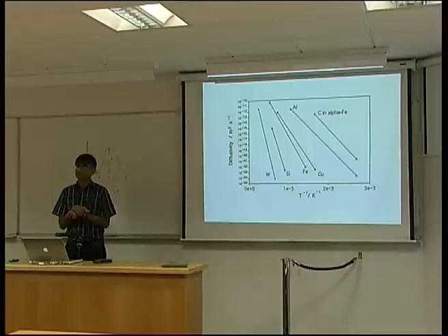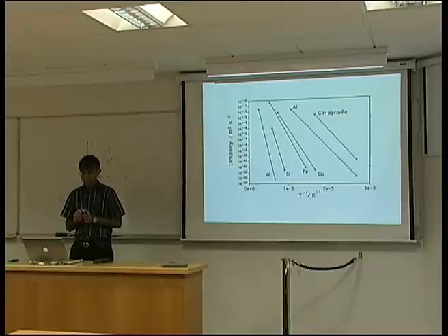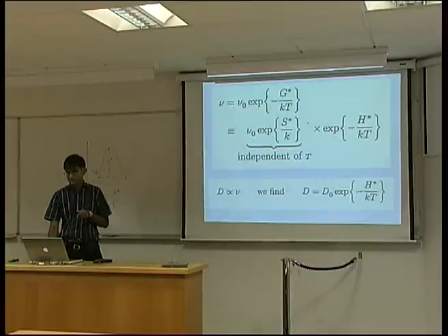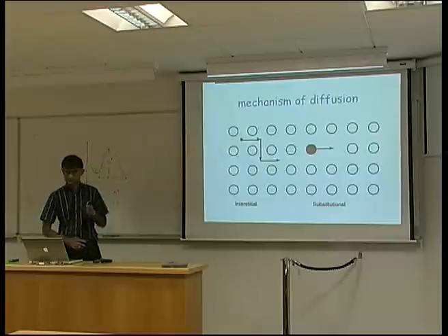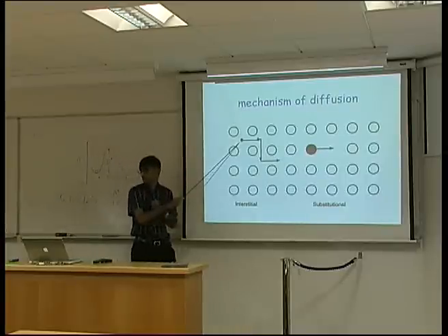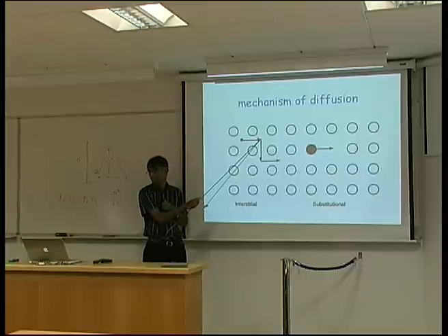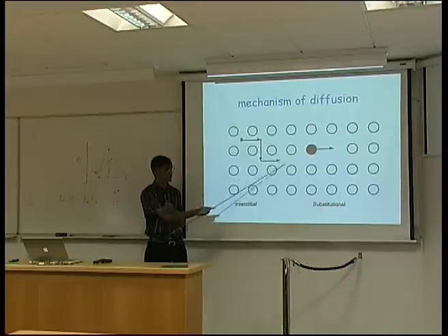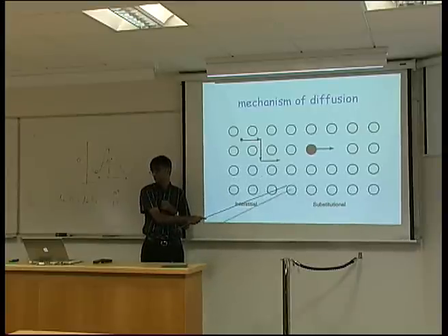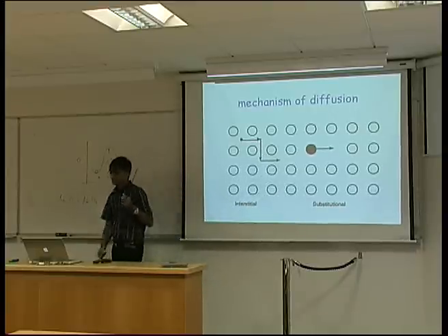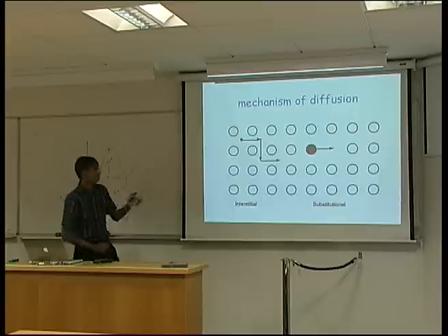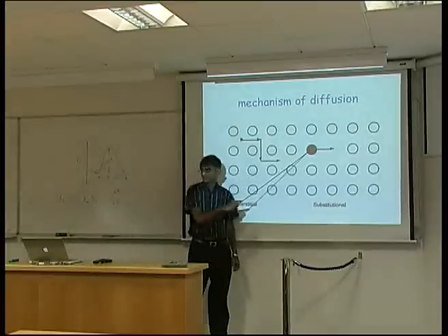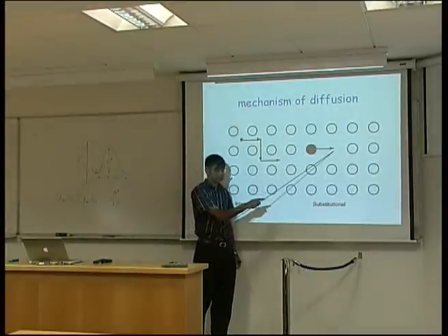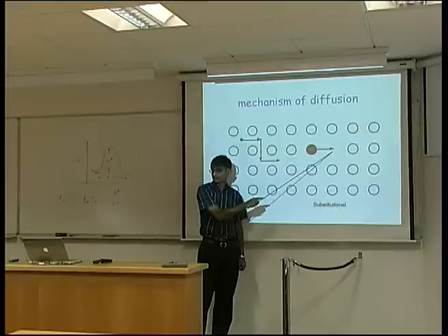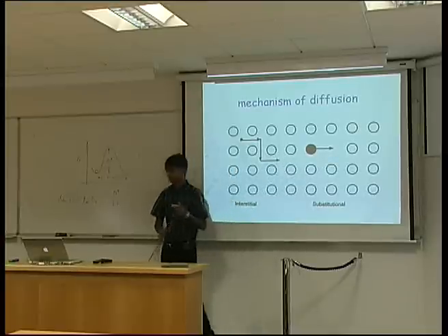Why is the diffusion coefficient of carbon so many orders of magnitude higher? Carbon is a small, lighter atom as compared to iron. Yeah, it's a small atom, so it sits inside the holes in the crystal, and it has no difficulty in finding vacancies next to it, because there are lots and lots of these holes. So it can move in between the large atoms. Whereas in the case of copper, it is like a substitutional atom, and there has to be a vacancy created next to it in order for it to move.